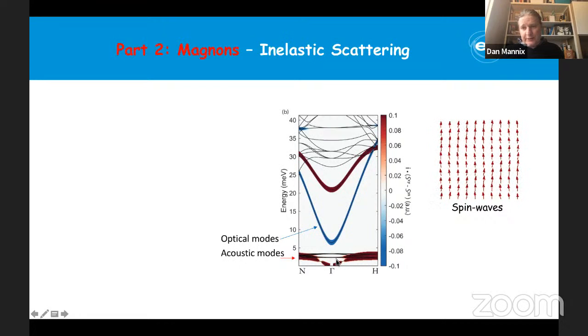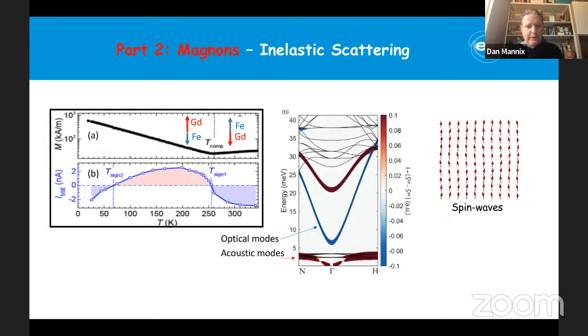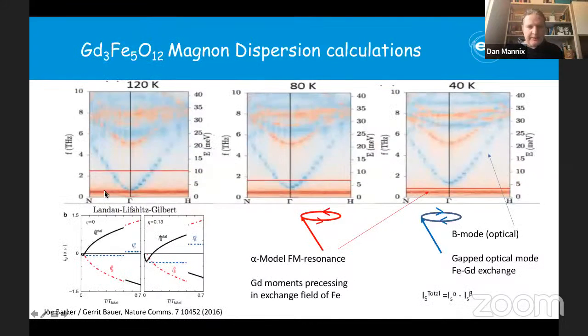Neutron scattering actually has beautiful energy resolution compared to X-rays, so that's where we use its strength, looking at bulk materials for these things. This is again to remind you, coming back to what this sign change is at lower temperatures, highlighting the magnetic effect. There's a theoretical paper by Gerrit Bauer and Joe Barker, which describes what happens at lower temperatures in this material, gadolinium iron garnet.